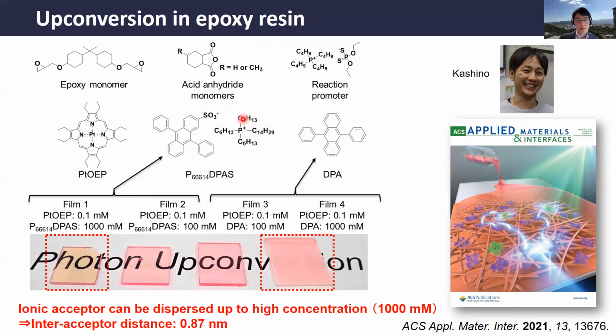We use this ionic liquid acceptor because it can be dispersed without phase separation up to a very high concentration, like 1,000 millimolar, so 1 molar. If you use the conventional DPA, it phase separates, crystallizes, and precipitates in the epoxy film, so you cannot get a transparent film. But with this ionic liquid, you can get a very transparent film, and the glass transition temperature is still above room temperature, so it's rigid at room temperature. You need such a high concentration because you can then get a short inter-acceptor distance of 0.87 nanometer, less than 1 nanometer, which is short enough for triplet exchange transfer.